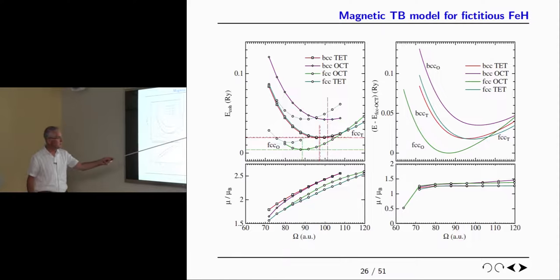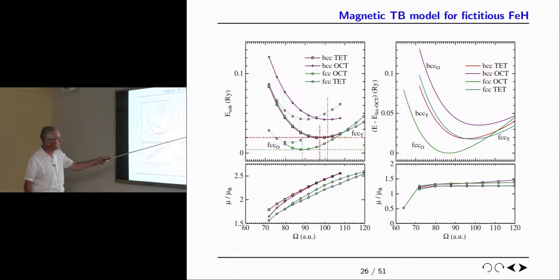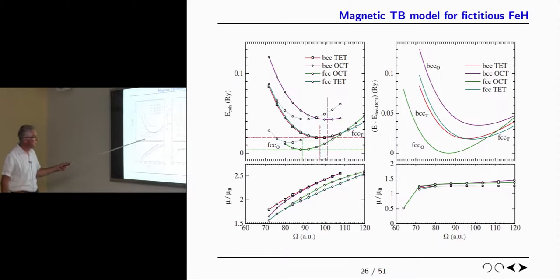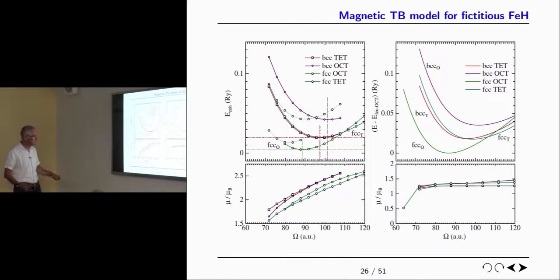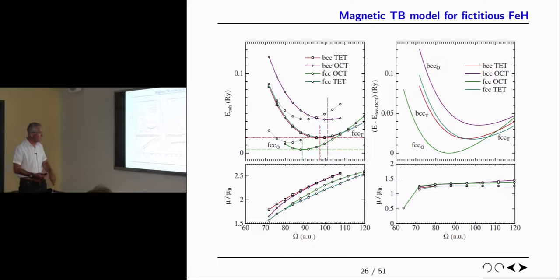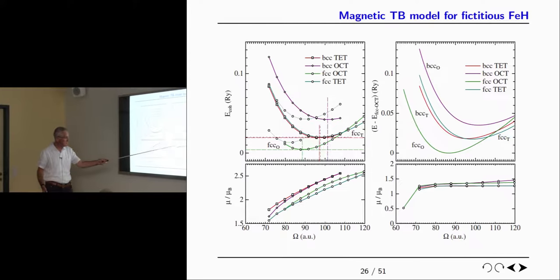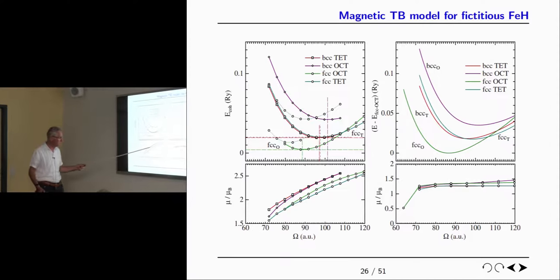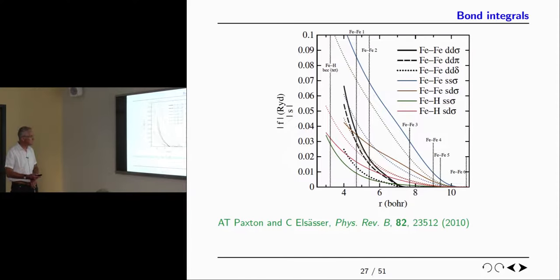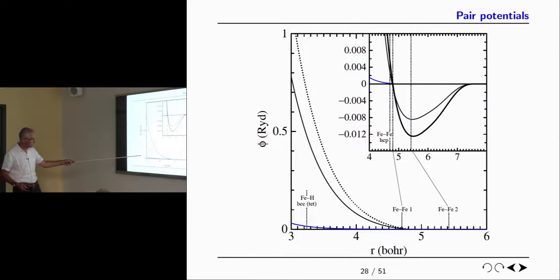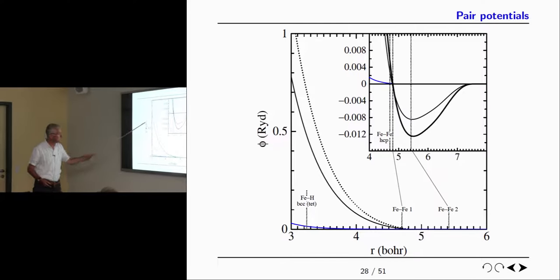So these are the tight binding results using the genetic algorithm fitted to those five data points, namely the minimum, the energy differences, and the atomic volumes. And these are the magnetic moments as a function of volume compared to the local spin density approximation. Just to remind you, this is the slide I showed a moment ago. These are the hopping integrals that were obtained, and the pair, you see the hydrogen-iron pair potential is this blue line down here.